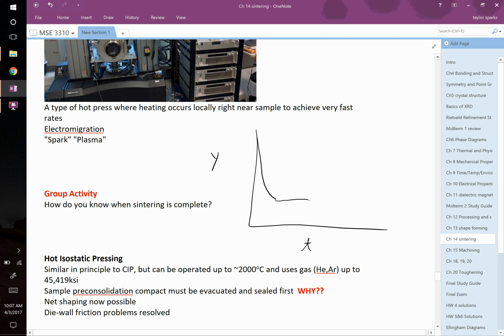And then it might start to sinter, but then it's going to go up slightly. When it starts to go up, you know that sintering is done, and it's still just getting warmer and warmer, so it's actually starting to expand. So you're done at that point. And this is really easy to monitor. Most of these things are built on an Instron frame, and you can monitor that crosshead displacement in real time, and it doesn't take very long.